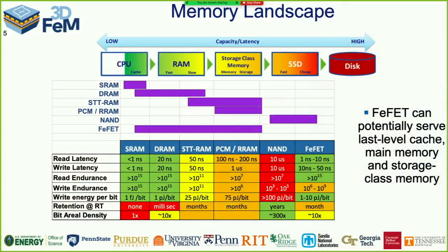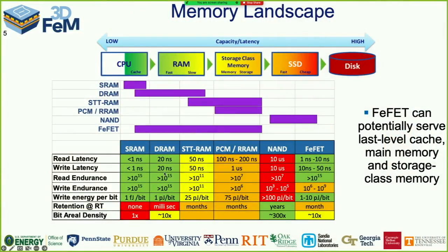And what I show here is a comparison of, so here's our central processing unit. Here are potential approaches to the various levels of memory. And here are some of the approaches to non-volatile memory that are being explored. So if it's non-volatile, I don't have to continually refresh it. I don't have to pay the energy burden of continuing to update the memory. So if we're going to put this memory on the processor, we'd like it to be non-volatile. And what's shown in green on this table is good. What's shown in red is likely to be a showstopper. And you can see that for STT-RAM, phase change memory, resistive memory, NAND flash, ferroelectric field effect transistors, none of these technologies are perfect. But we got a fair amount of green here for the ferroelectric field effect transistor.